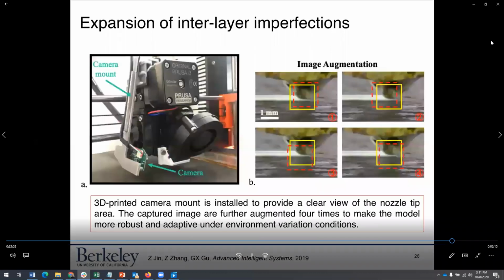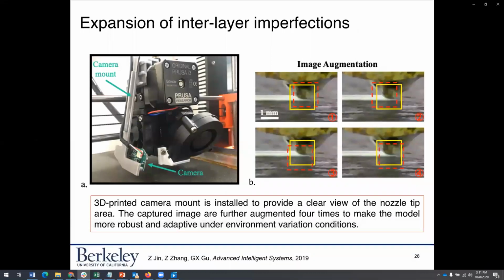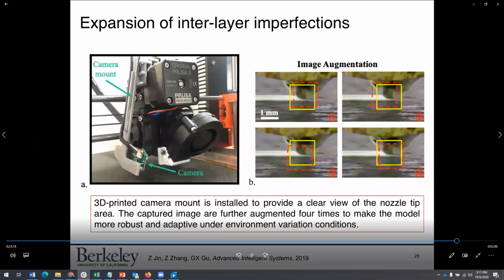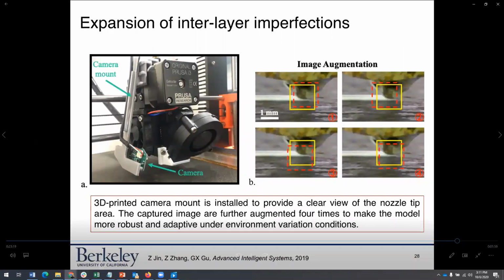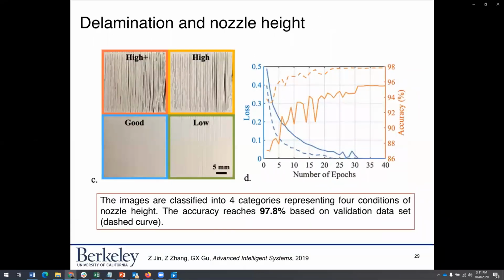In addition to these in-plane issues, we were also looking at out-of-plane issues, such as delamination and warping. In this case, our camera location is going to be slightly different. It's going to be on the side, so we can look at delamination. Delamination is slightly different from under extrusion and over extrusion. It is usually dictated by a process parameter called nozzle height, which is how far your nozzle is from the print bed.